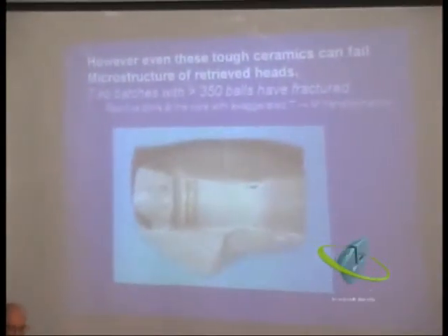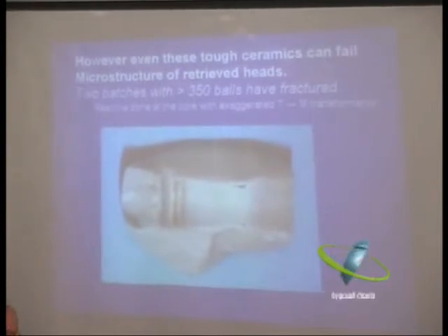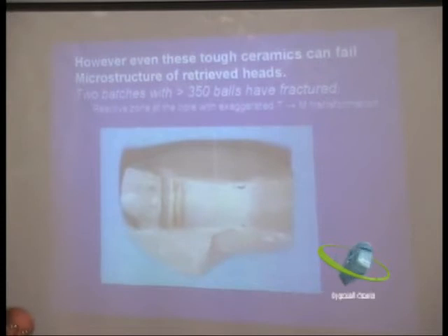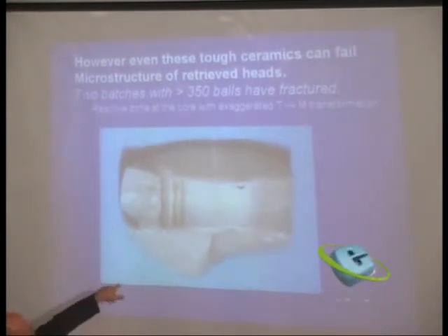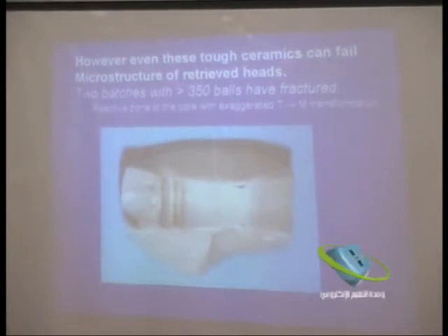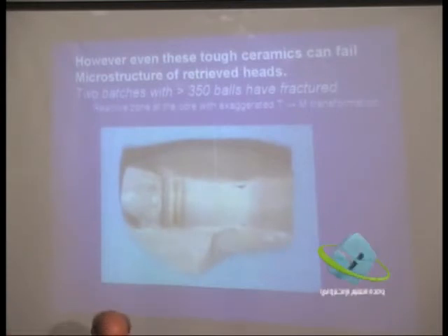And now, if this is around a spike, for instance, in the orthopedic conditions, around the Morse taper system, because we place the ball over the top of that, if this occurs on the inside, then it's like a pressure vessel. It's getting more and more pressure as this transforms, and these cause these systems to break. This is a worry I have with zirconia being used for implants, because a lot of people are interested in this process, but with an implant, this is likely to be there for 20, 30 or longer years. And so this question of does this process occur is very, very important.